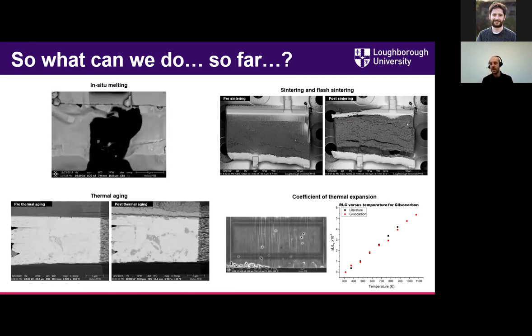For composite materials, you can't necessarily measure CTE manually because the sample size is so small. So what you can do is prepare a FIB lamella and heat it up and look at its change in length dependent on temperature. And that's been quite a fun little area of interest.